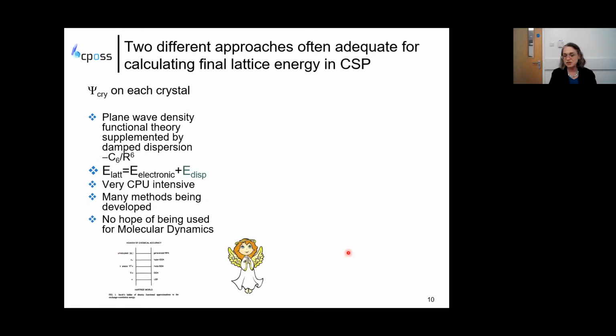So this means that there are currently sort of 2 camps of approaching doing crystal structure prediction. Conceptually, the easiest one is that you try and attempt to solve the Schrödinger equation for each of the low energy crystal structures you've generated, and that will give you the relative energies, or at least these lattice energies. But the problem is that organic crystals are held together by the sort of van der Waals forces, the dispersion, instantaneous correlation of movement of the electrons, which is very difficult to capture in electronic structure theories. And so there are increasingly accurate, mainly density functional theories being used with added dispersion, but they're pretty inaccurate on the grand scheme of theoretical chemistry, and very expensive and can't be used for molecular dynamics calculations or putting in molecular motion at all.